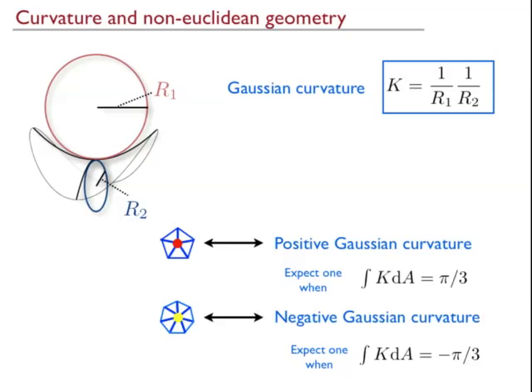Here's a hexagonal sheet in flat space, right? If what I do is I take this and I get rid of 60 degrees like this, in flat space, this just distorted the hell out of the surface. The strain fields were enormous. They went like R squared and stuff like that. Here, I haven't strained anything. All the lines I've drawn here are exactly the same. But I have something which is no longer flat. And it's got positive Gaussian curvature.